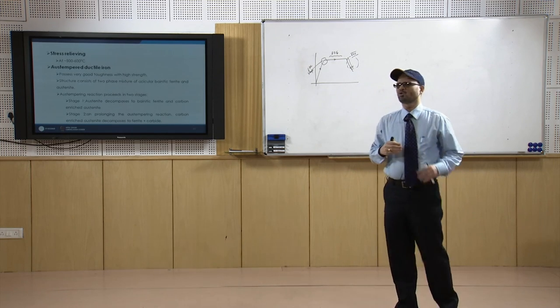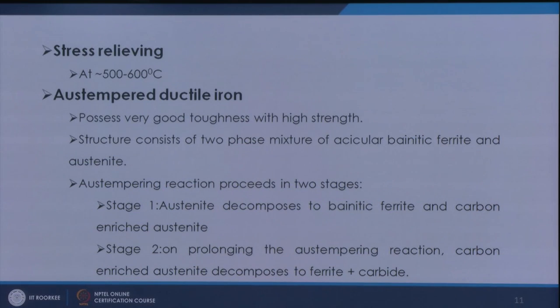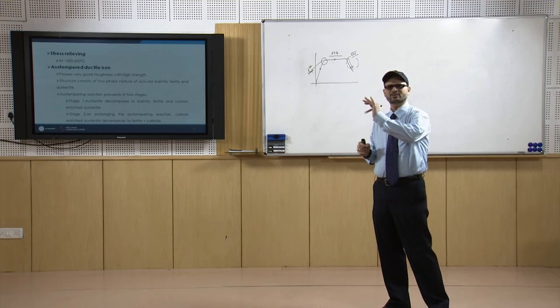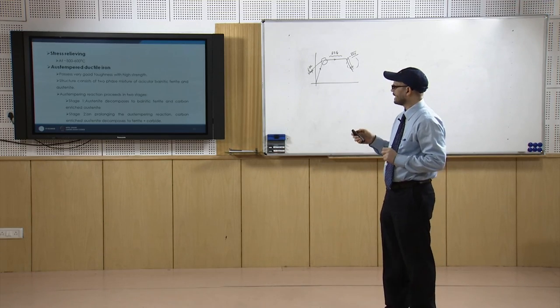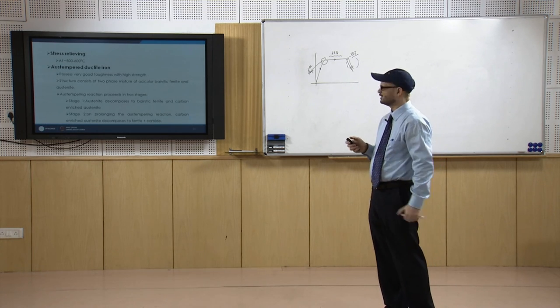Then we also go for stress relieving, which is done normally at 500 to 600 degrees centigrade. You retain for some time and then cool slowly, so that basically relieves the stress in the material.